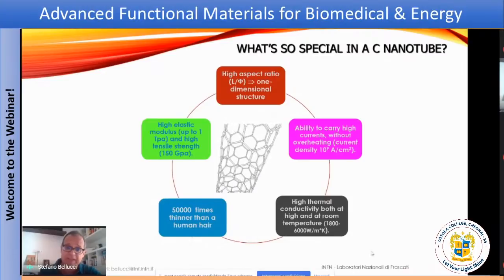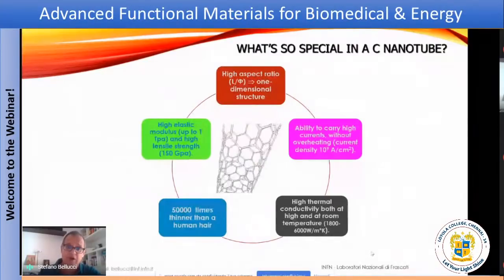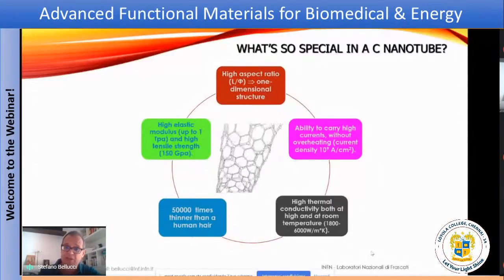What's so special in a carbon nanotube? First of all, as I said, it's high aspect ratio, which makes it a one-dimensional structure, but also its elastic modulus. Its Young modulus can beat any special steel that is in use, very easily above 1 terapascal. Also, the ability to carry high density of currents can outdo the current density transported by copper, and it can reach 10 to the 9 ampere per square centimeter. Moreover, from the thermal point of view, it has a very high conductivity at different temperatures, from room temperature up to very, very high temperatures. And these values are exemplified here, several thousand watts per meter per Kelvin.